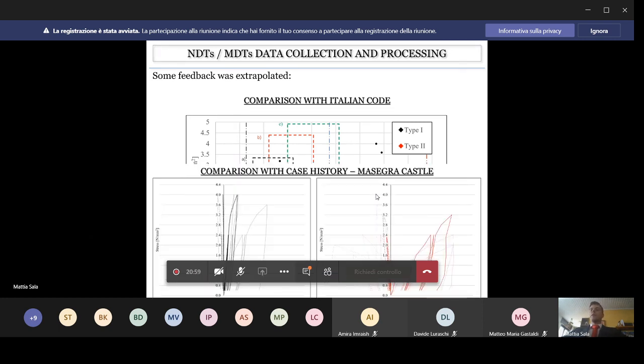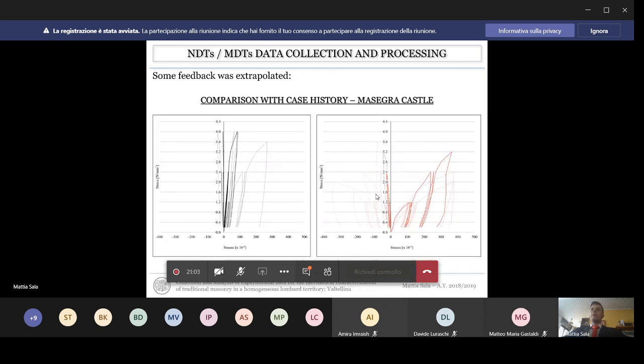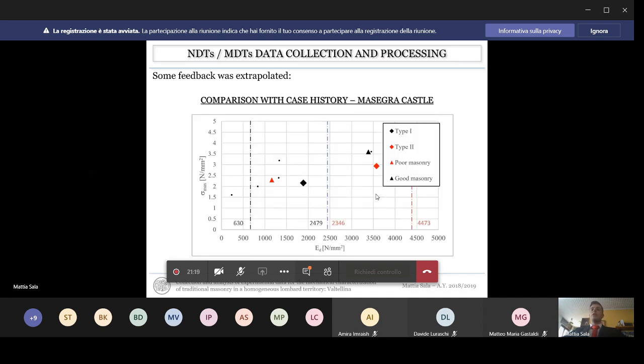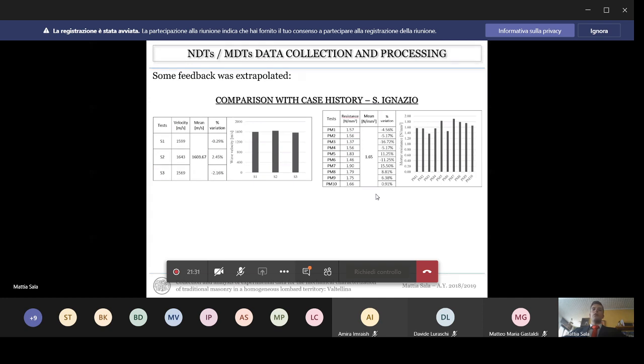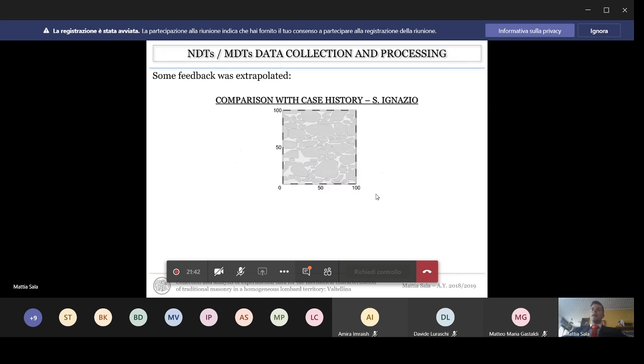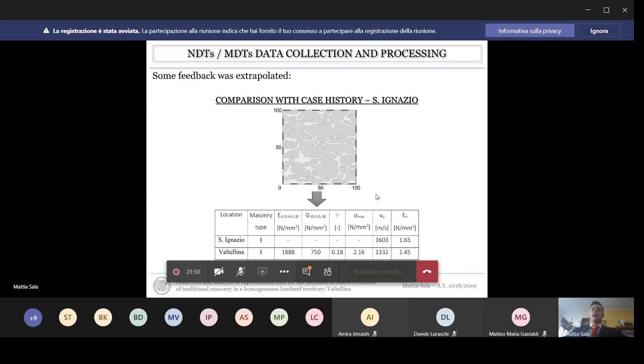The next comparison was with the case histories, and regarding Masegra Castle, dividing the masonries according to their texture, this classification matches also in this case with the mechanical properties. This is confirmed also by the compressive strength versus the deformability modules graph, where the mean values match with the mean values highlighted for the type 1 and type 2 of Valtellina. In the comparison with Sant'Ignazio, only indirect tests were performed, with sonic wave velocity and the penetrometric test, and the mean values found are in line with the values found for the typology 1 of Valtellina. Moreover, we see the masonry was made with a disordered texture, and for this reason, the mechanical properties of Sant'Ignazio church can be taken with a good approximation similar to the typology 1 of Valtellina.